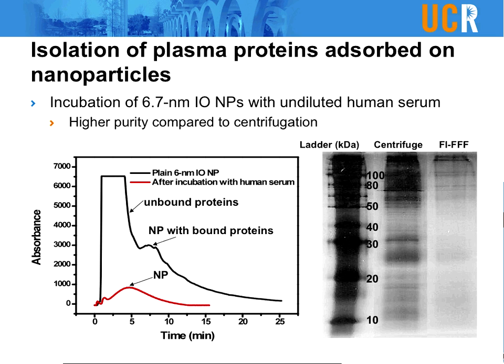So anyway, when we analyze the gel, we find much fewer proteins on the preparation with FI-FFF. And since these high molecular weight bands are there, we will say that those could be the co-eluted proteins. One way to discriminate that is to inject the plasma protein only into the system, and then collect it and analyze it on the gel and see if the same bands will show up. But that research is still ongoing in our group.